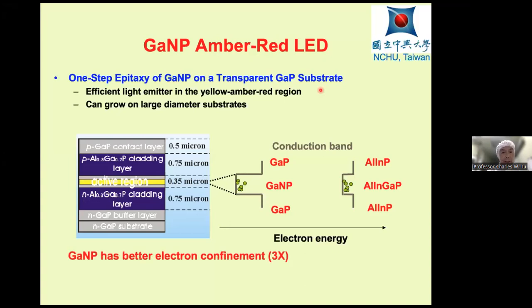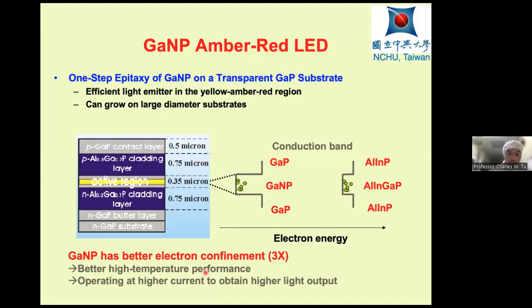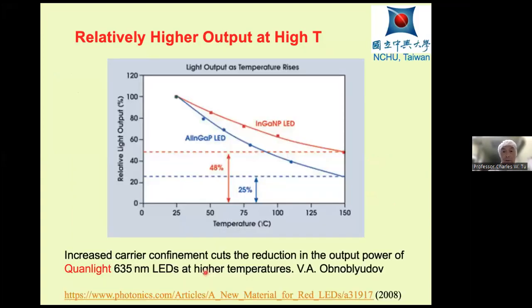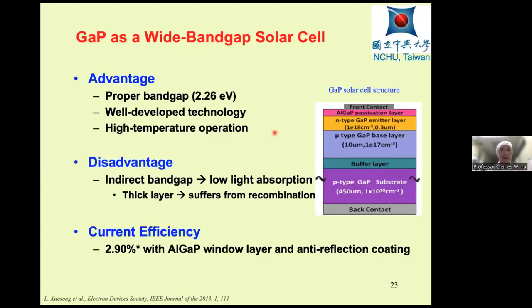And so here we have gallium nitride phosphide compared to the regular LED. We have 3 times better electron confinement, so better high temperature performance, and we can operate at higher current. Actually, my student and I formed a company to do this, and this is done by the company. We compare light output as a function of temperature, and you see that at higher temperature, this dilute nitride LED has a larger light output. So that's about the LED, how it improves the LED.